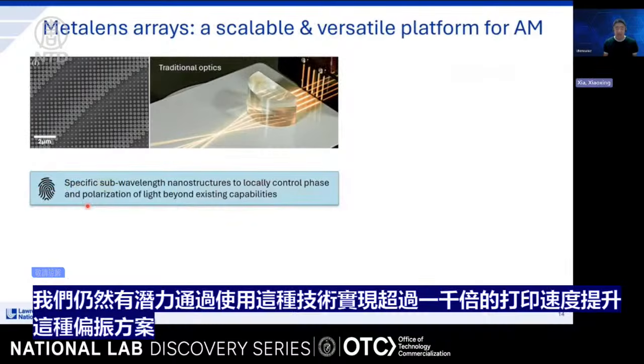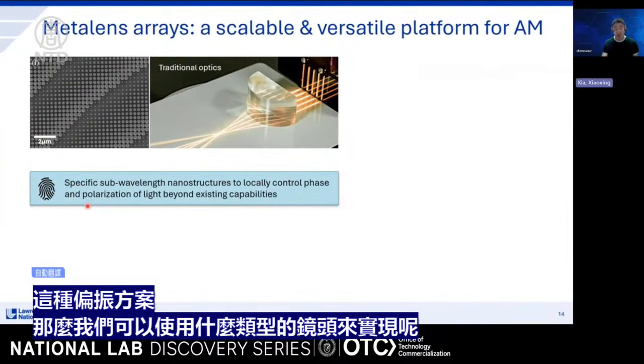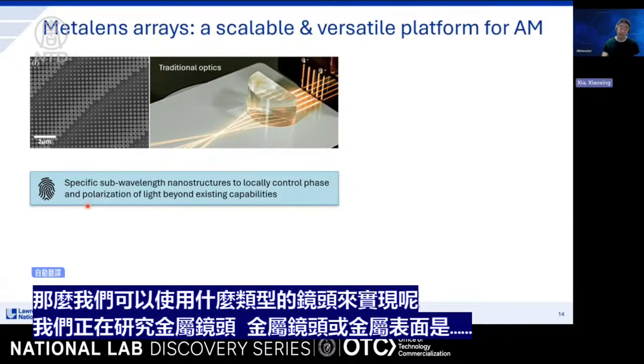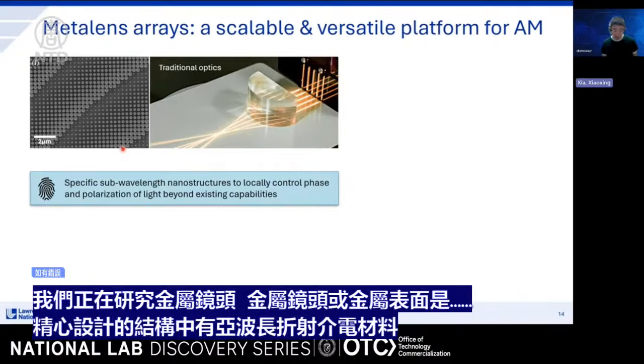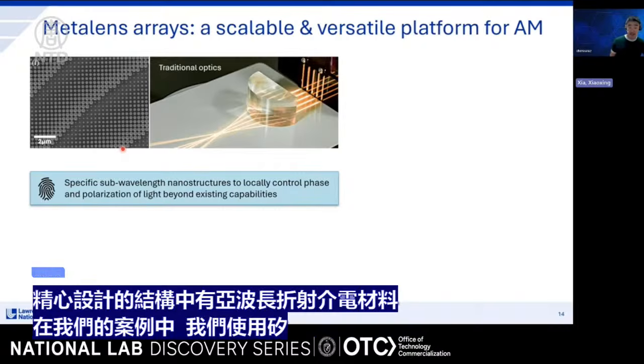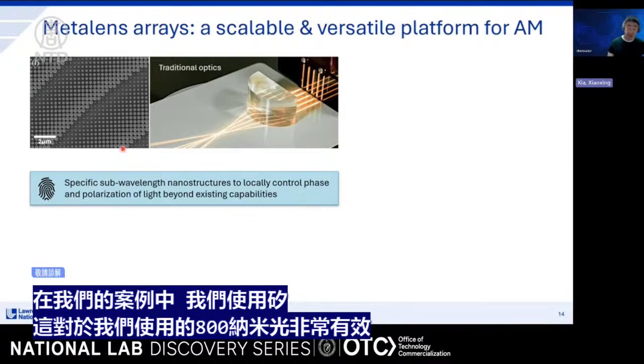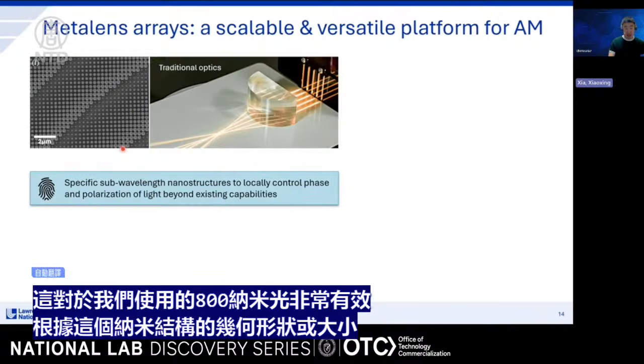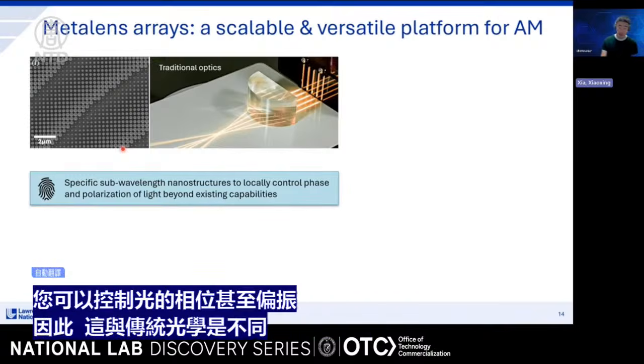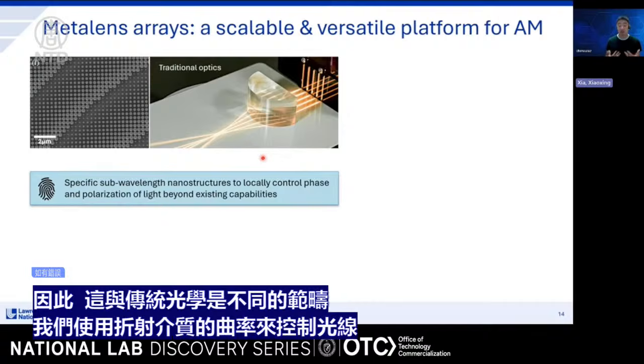So what type of lens can we use to make this happen? We're looking into meta-lens. So meta-lens or meta-surface are carefully engineered structures. They are sub-wavelength refractive dielectric material. In our case, we use silicon, and it's very good for the 800 nanometer light that we use. So depending on the geometry or size of this nanostructure, you can control the phase and even the polarization of light. So this is a different regime compared to traditional optics, where we're using the curvature of the refractive media to control the light.